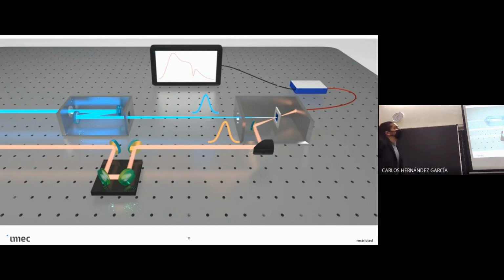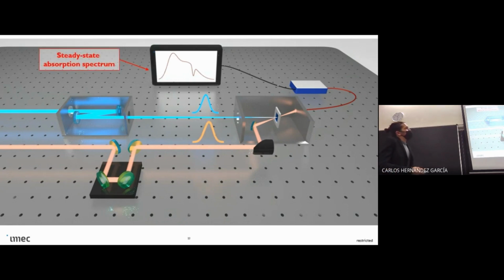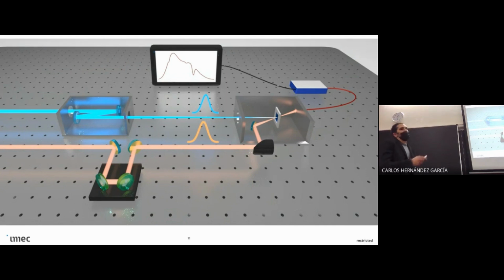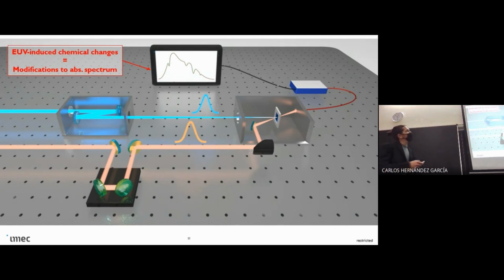And so what this looks like is we have our EUV beam coming in, hitting our sample, and a mid-IR probe beam. Before the EUV light hits, we might observe a static absorption spectrum, some kind of characteristic peak of a molecule or vibrational mode. As we change the time delay, when the EUV comes first, we might see the appearance of new peaks. And as we further scan this time delay, we'll see the appearance of new peaks, the disappearance of our original peaks.